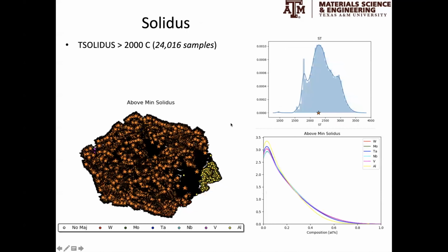If we look at the solidus, it turns out this space is pretty good at having a minimum solidus above 2000 Celsius. This is how the histogram of solidus looks like. In general, most of the alloy space satisfies these constraints, except for the aluminum corner of this high entropy alloy space.